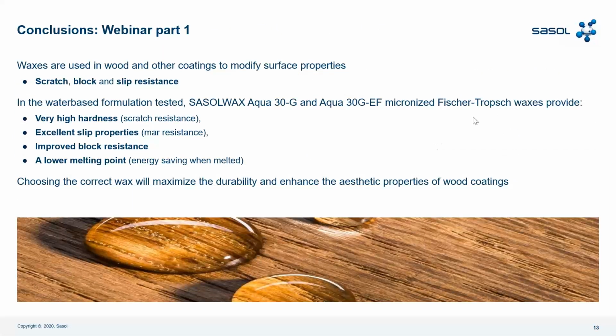We can continue. As I mentioned before, the waxes are used in a water-based solution for scratch resistance, block resistance, and slip resistance. Again, Sasol Wax Aqua 30G and Aqua 30GF achieve the best performance and show very high hardness, which means good scratch resistance. They show excellent slip properties. They improve the block resistance in your system, and also have a lower melting point compared to possible competition. That means energy saving when they melt, in a cooling temperature system. So I suggest you choose the right wax for your future formulation.